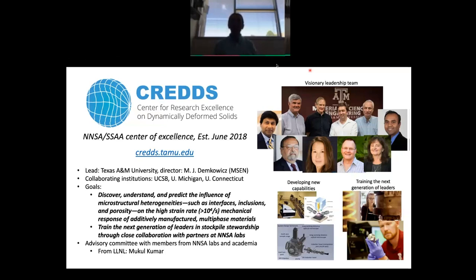And one of the ways that we can actually verify that is because we can calculate rates of radiation-induced mixing from our simulations. And radiation-induced mixing rates have been measured experimentally. We can compare our calculated radiation-induced mixing rates to the experimentally measured ones, and they match up basically perfectly. I mean, to within the uncertainty of the calculation and the experiment, they're the same. So we have high confidence in those cases. I would not have high confidence in cases where the liquid phase properties of the potential are not known.